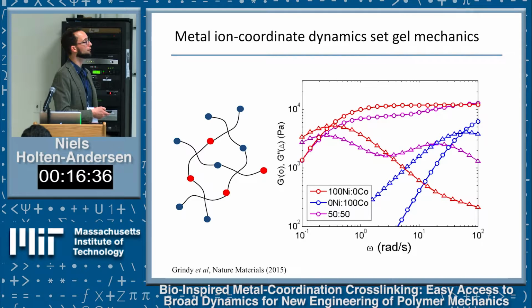When you do a 50-50 network, you see two of these energy dissipative peaks, which shows you have energy dissipation built into the network purely from the type of crosslinks you have in there. You also see that the elastic response, at a certain time scale, makes the network get stiffer.